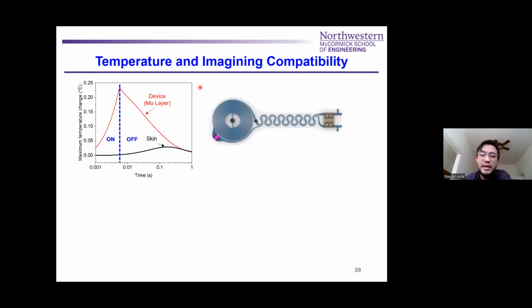Then you have also temperature and imaging compatibility. So in this case, if you're harvesting energy and powering your system to pace the heart, you can have an on and off pulse sequence operation, where as you turn it on, you're going to have a rapid increase in temperature on your conductive element, in this case the molybdenum layer, just because the conductivity is orders of magnitude higher than that of skin.